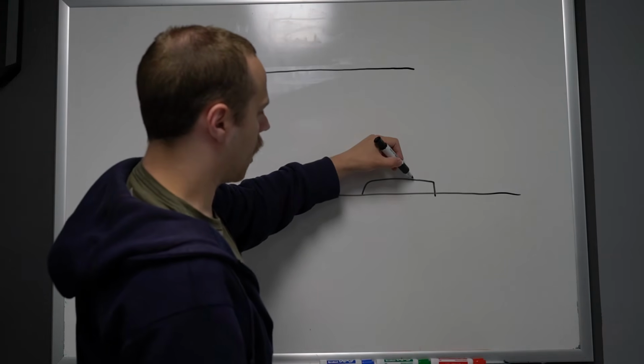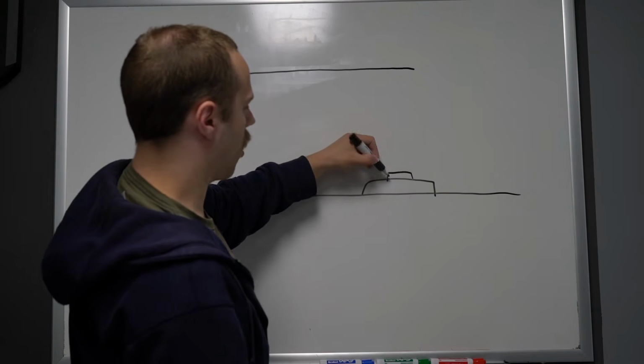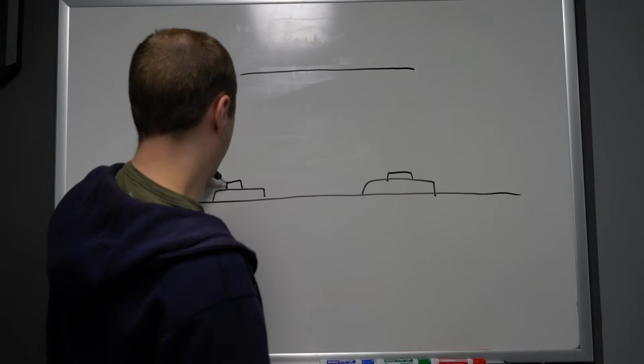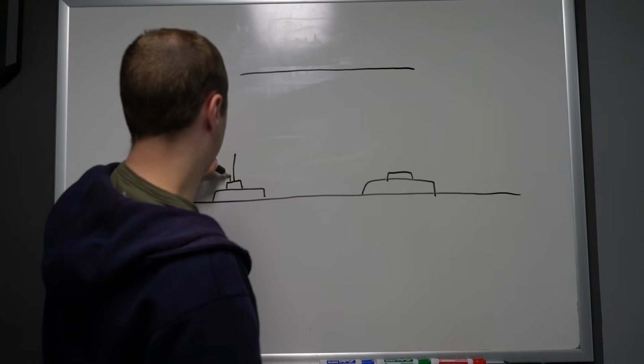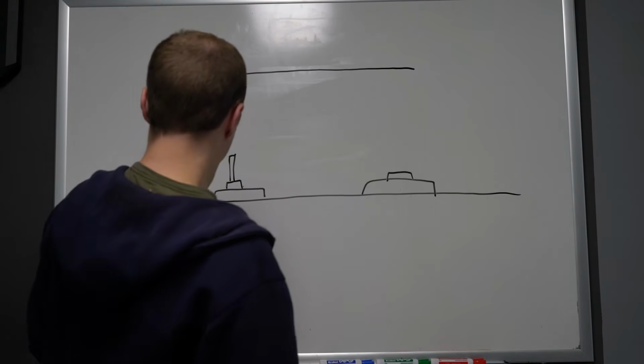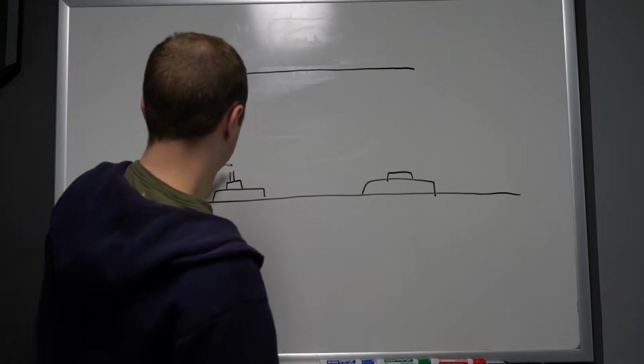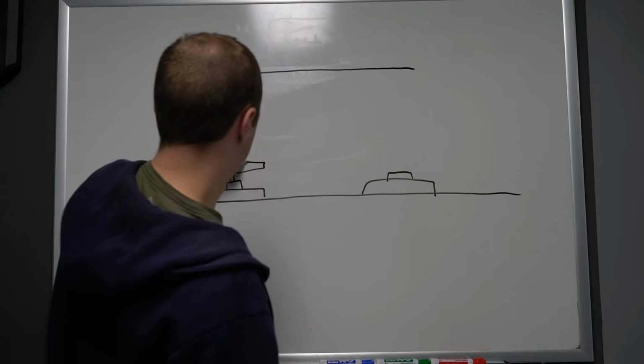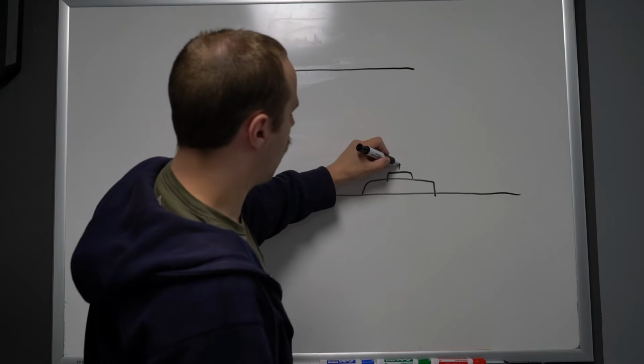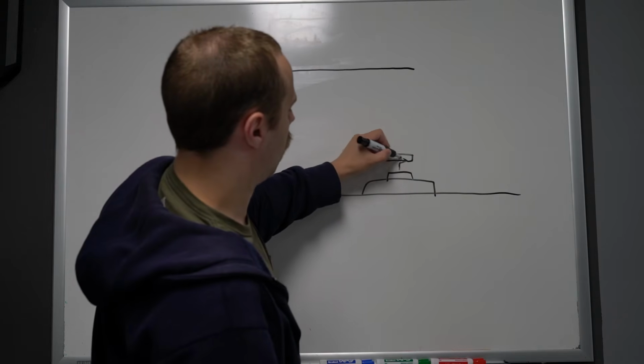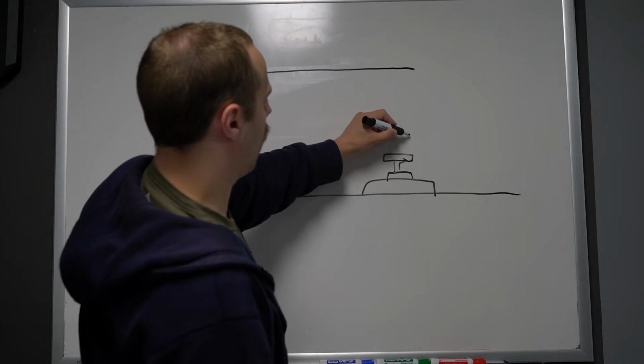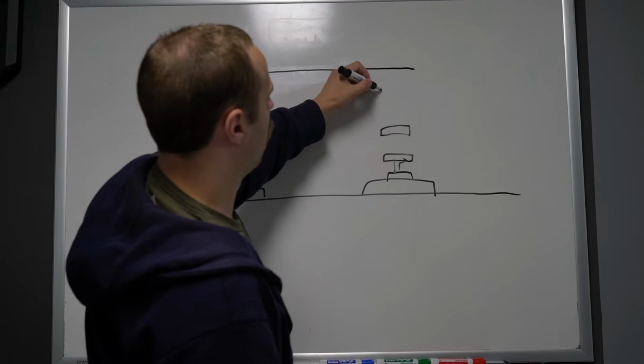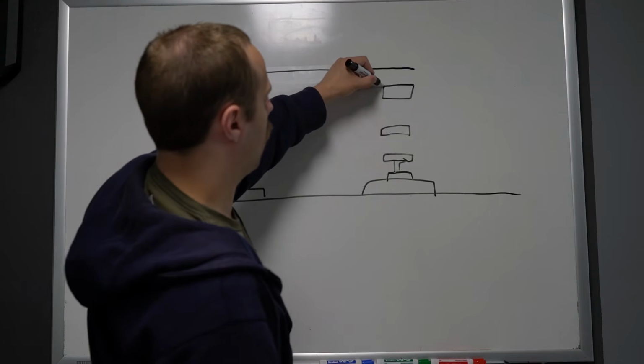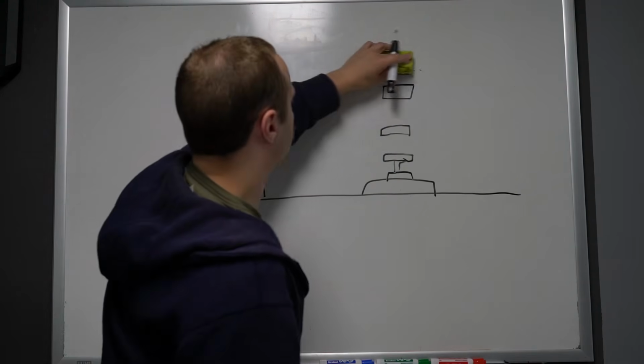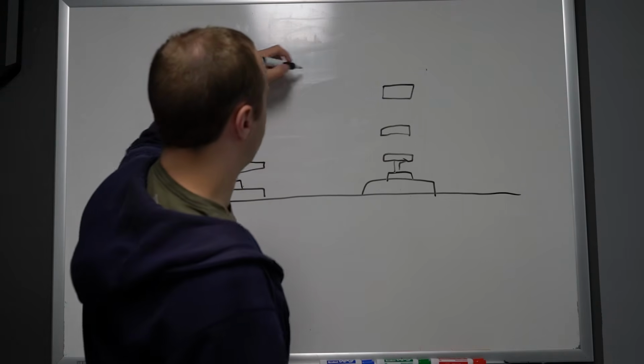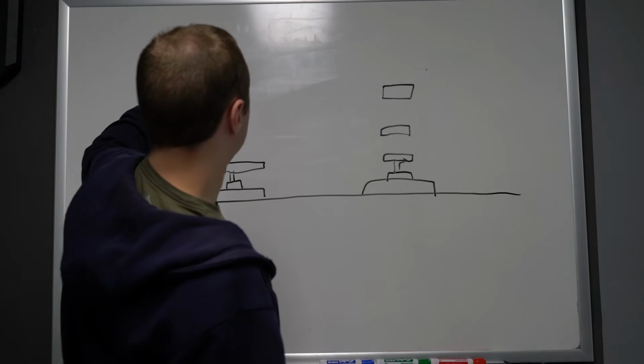Then we'll have our dielectric that's too thin to see. We've got our polysilicon gates going up above them. Contacts going from that up to, contacts should be that tall. Contacts going up to our metal 1. And then above metal 1, we're going to have metal 2, and then metal 3. And there's also going to be a little bit of roughness on the top surface, so the top passivation is actually not going to be quite flat.